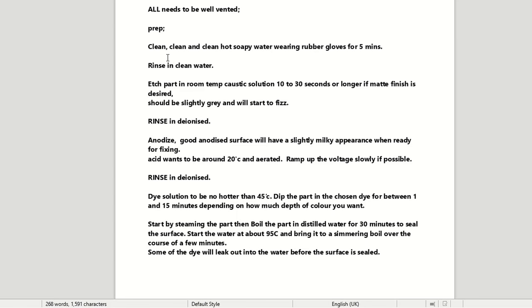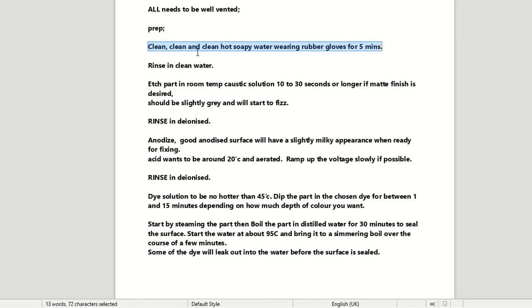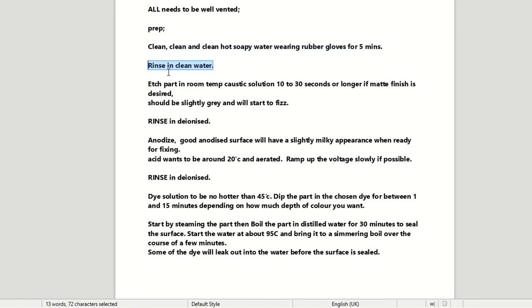So preparation, we want to clean, clean, clean in hot soapy water, wearing rubber gloves for five minutes. Now on the video, I wasn't cleaning that often. There's a whole lot edited out. You want to wear your rubber gloves and that'll stop any fingerprints or organic matter getting onto there, which will then also stop the process of anodising. So you want to rinse it in clean water. You don't have to do it in deionised or distilled water here. This bit's fine.